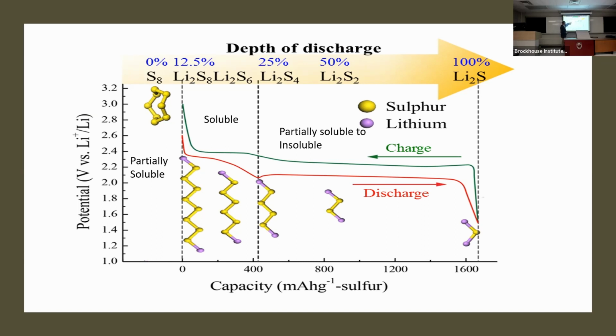And then as the discharge progresses, it forms other polysulfides, which are partially soluble to insoluble. And finally, it becomes Li2S, which is fully insoluble. So you start with an insoluble material and end up with an insoluble product. And that makes the whole morphology construction very, very difficult. Because, by itself, sulfur is insoluble and non-conducting, and lithium sulfide is a highly insulating solid. The reaction will not take place on the surface. There is no pathway for electrons and ions. So you need, in a morphology, to connect this to a conducting material like carbon, for example.